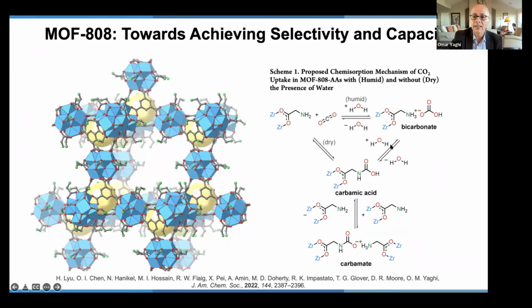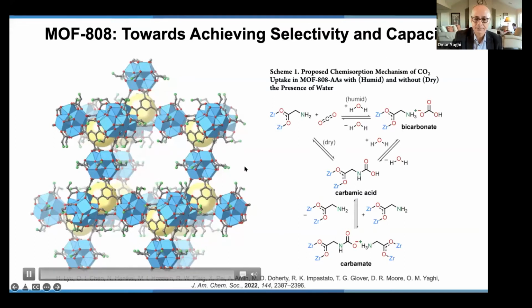Now, in systems where, for example, you are extracting CO2 from air, this is the mechanism that would be operational, in that now you have to make carbamate or carbamic acid, depending on the pH, and that requires some heating, 40 to 90 degrees, depending on the system, to remove the CO2. What I'm trying to say here is that as CO2 penetrates through the pore, there are different chemistries that take place depending on whether the CO2 is coming in high concentration from flue gas or in low concentration from air. And accordingly, the chemistry in the pore can be adjusted.